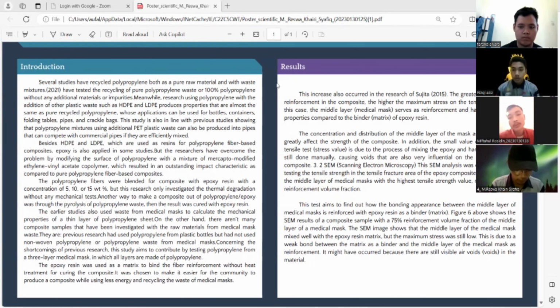Figure 6 above shows the SEM result of a composite sample with 75% reinforcement volume fraction of the middle layer of a medical mask. The image shows that the middle layer of the medical mask mixed well with the epoxy resin matrix, but the maximum stress was still low. This is due to a weak bond between the matrix as a binder and the middle layer of the medical mask as reinforcement. It might have occurred because there are still visible air voids in the material. Thank you.